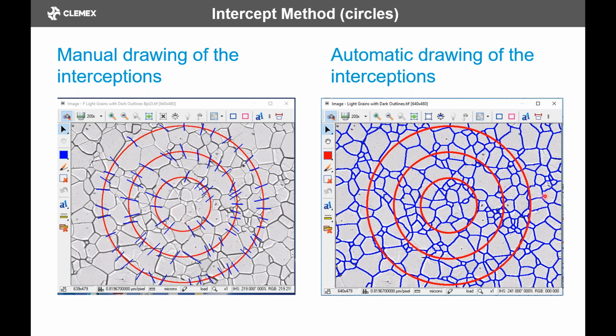On the right, we have a similar approach, but here, because the grains are defined, you can detect the grain boundaries and still do an intercept. The idea here is that we used the mouse originally, but the software will detect the points at which there's an intercept and will count them. So if someone says we need to do an intercept method for grain size and we need to have the circle, you can do that automatically if you can detect the grain boundaries.